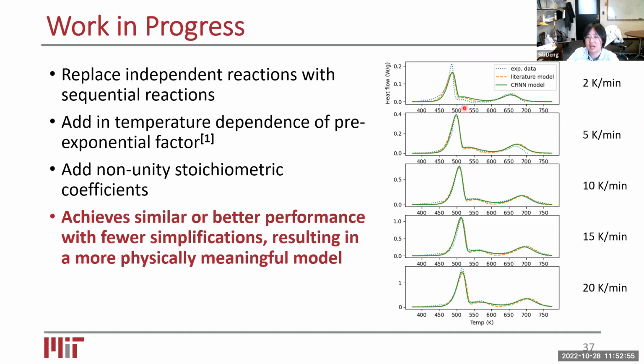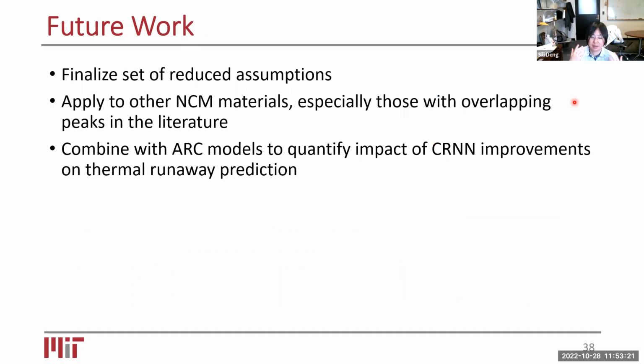And you can see the green curve, which is the CRNN model prediction. It matches with experiments very well, no worse than the ones with assumptions. So we hope that with this framework, we can really help the community understanding what's governing the thermal runaway of batteries, and be able to mimic the more realistic scenarios.